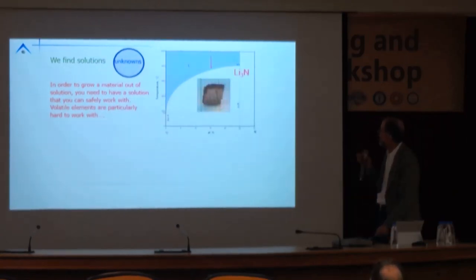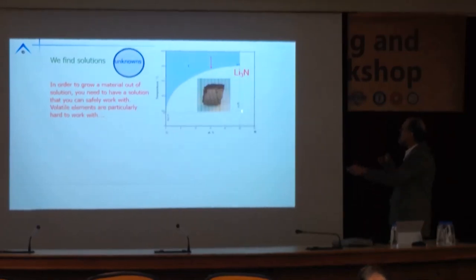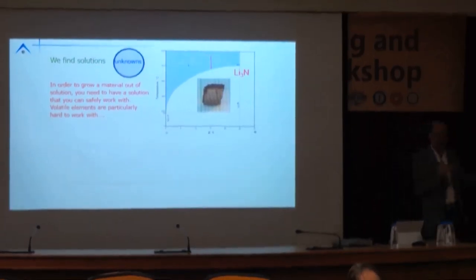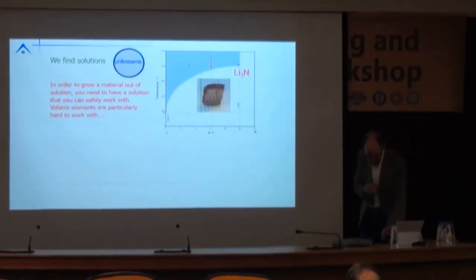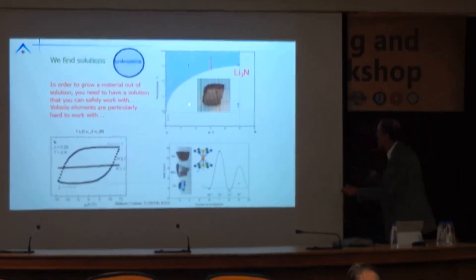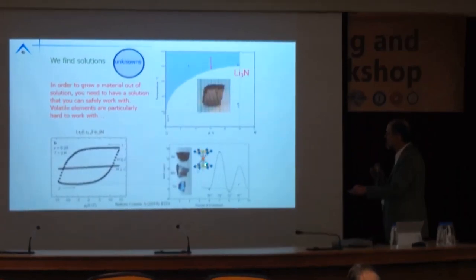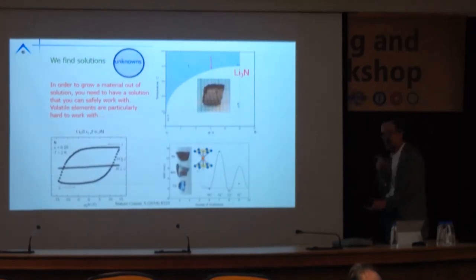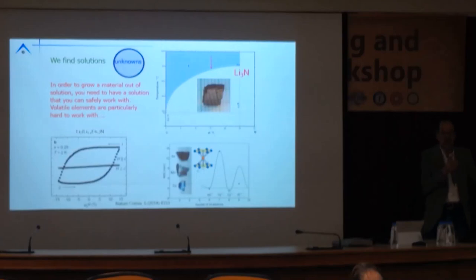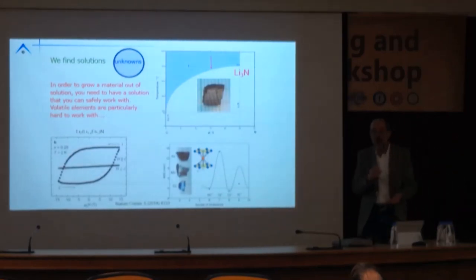Okay, good. All right. Now, what we could do is we could add polycrystalline lithium 3 nitrogen to lithium, and we could grow a huge single crystal, which tells you this is actually working nicely. Okay? With that done, we figured out there are two lithium sites, one in a highly one-dimensional configuration between two nitrogens. If we substitute in a transition metal, we've got single ion magnetic anisotropy greater than the rare earths. You know, if you're talking about magnetism, this is a holy grail. Now, it's in the lithium system. It's not going to be all that practical, but it's a fascinating physical discovery.